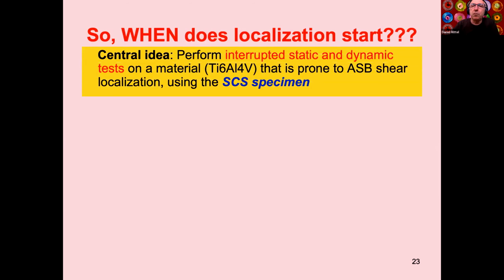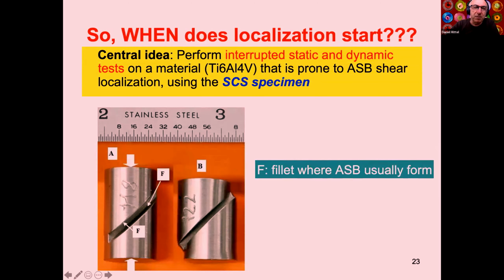So for that, we perform interrupted tests. We simply put stop rings on a Hopkinson bar, use a very nice specimen, the shear compression specimen that was invented in 2000 at Caltech with my colleague and friend, Professor Ravi, and Dr. Sang-Wook Lee. And this is a specimen in which the kinematics enforces a state of dominant shear, but not pure shear and not simple shear, but dominant shear. And you can use this specimen statically and dynamically alike, perform some shear dominant experiment.